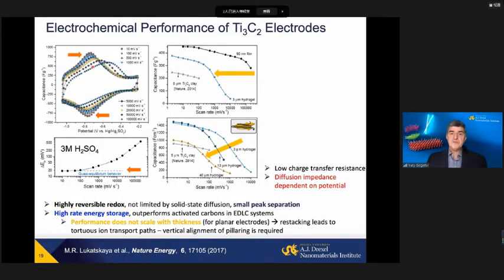Moreover, if you look more carefully and take thin film electrodes and charge and discharge them in sulfuric acid solution, it's very interesting. We get a double layer envelope and we get this broad reversible peak. Moreover, up to rates of maybe 5 volts per second, it's electrochemically reversible. So the separation is less than 20 millivolts between the peaks here.